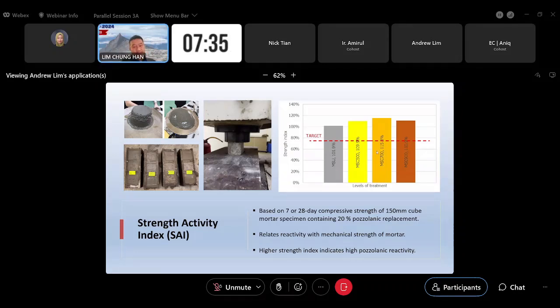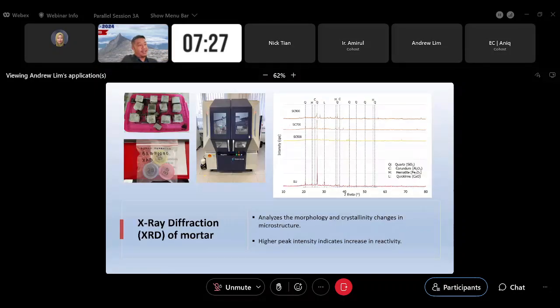So this is the first method I'm assessing the pozzolanic reactivity with, the strength activity index, based on strength. The second method is very different compared to the first. The second method is based on XRD, which is very similar to what Dr. Parimon did earlier. This method bases the pozzolanic reactivity on the morphology and, more importantly, the crystallinity of the material.